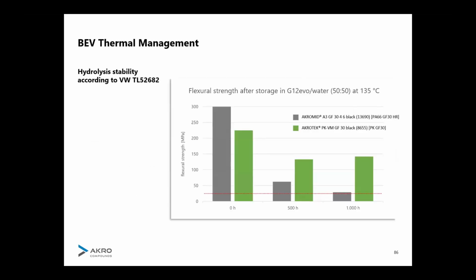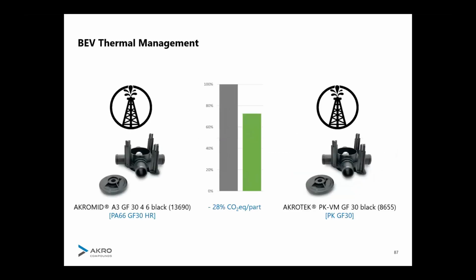kind of applications. So we heard already a lot about hydrolytic resistance, about the test results. I'm glad that the numbers we saw so far match with what I prepared, but we do not need to go through this chart again. What is also interesting is the sustainability aspect of polyketone. Just comparing two fossil-based materials, a nylon 6,6 with 30% glass fiber, or a polyketone with 30% glass fiber, you see, without using any kind of recyclate or doing anything really fancy, you already get close to 30% reduction in carbon footprint. That's quite something.